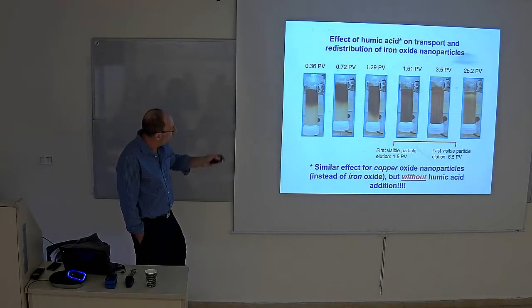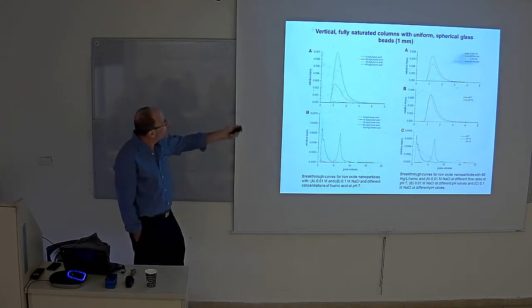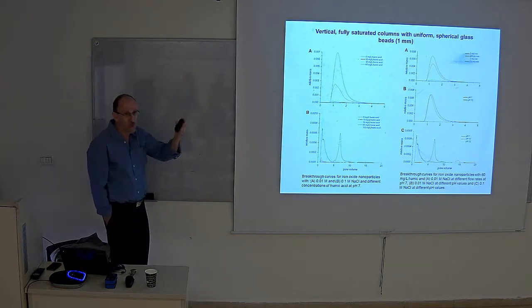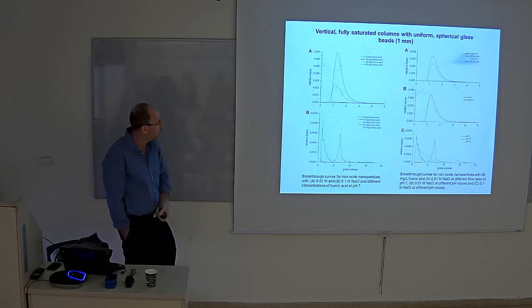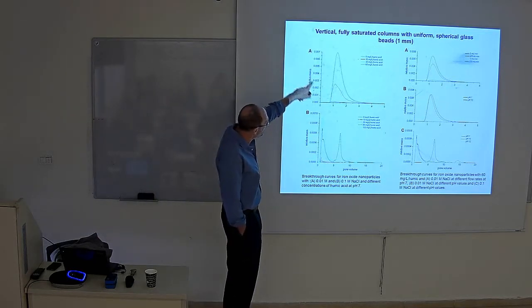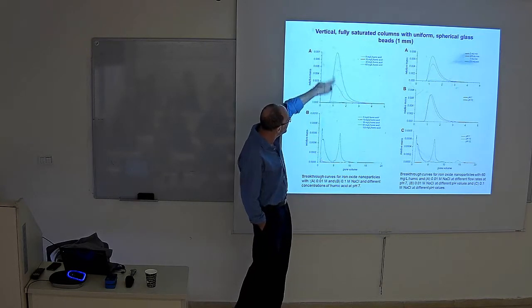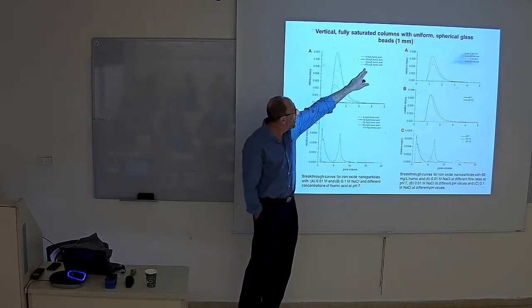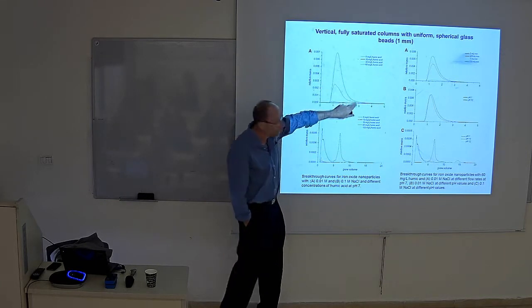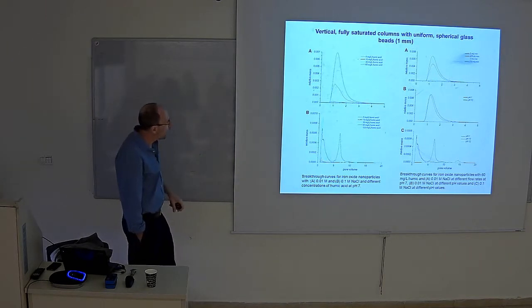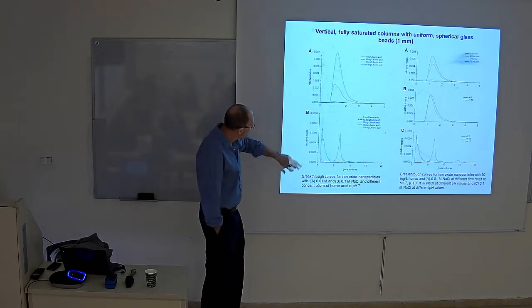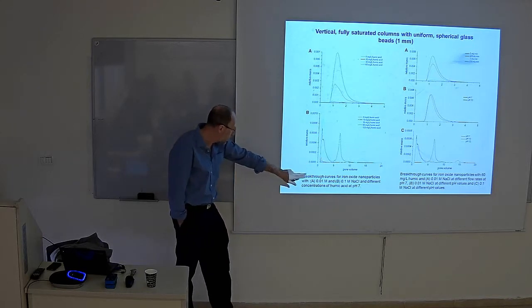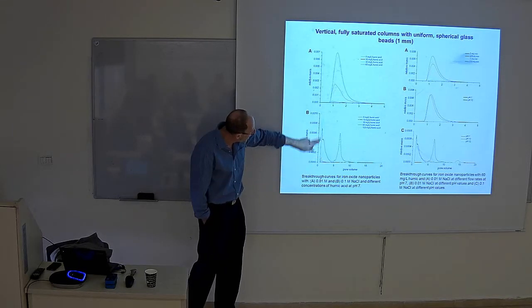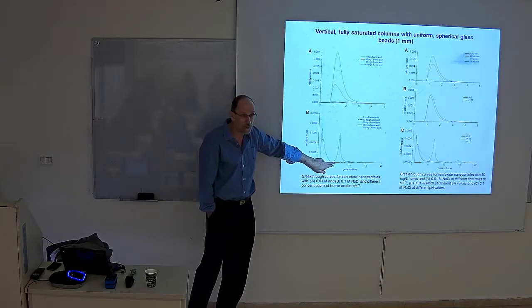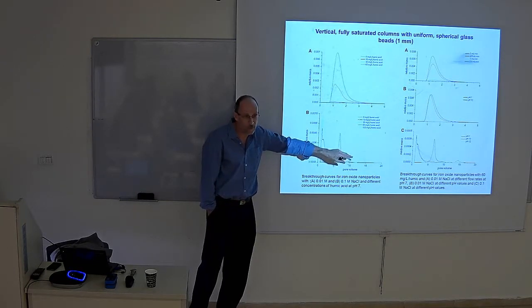Oh, one other thing I want to show. So then we thought also, so let's play further, fully saturated, and again, this is glass beads. What does the breakthrough look like once they start coming out? And one expects usually, if you look at the mass for a pulse of particles being put in over a number of pore volumes, you expect that kind of a nice pulse breakthrough curve. Add more humic acid, it becomes more mobile, so we get those kinds of pulses. There are many cases, though, with different salt concentrations, different pHs, this is different salt concentrations, same pH, where you get a pulse of material coming out, and then nothing, then another pulse, and afterwards another pulse.